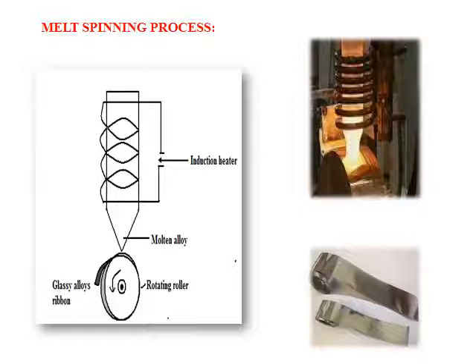The ejected melt is cooled at a faster rate on the spinning cooled copper disc. The ejection rate can be increased by increasing the pressure of the inert gas at the top of the refractory tube. A glassy alloy ribbon starts forming over the spinning disc, and its thickness may be varied by increasing or decreasing the speed of the spinning disc. This is a simple method for producing ribbon-form metallic glasses.